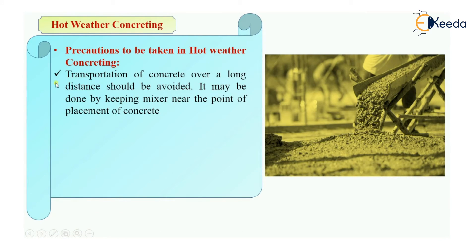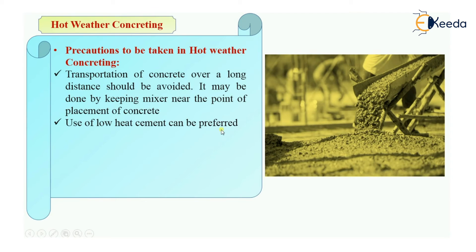Transportation of concrete over long distances should be avoided, because in high heat the concrete may start setting in transit or you would have to add more water, which reduces strength. You can keep the concrete mixer near the point of placement. Use of low heat cement can also be preferred, and chilled water for curing shall be adopted.